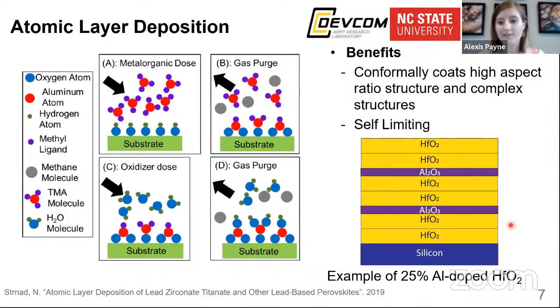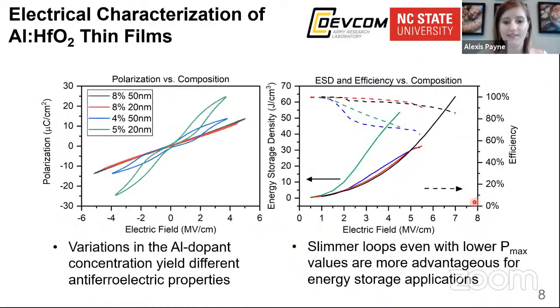In this case, you can see that there are 8 layers, and out of those 8 layers, 2 of them are alumina, making this example film 25% aluminum-doped hafnia. That's a really high doping concentration compared to what we use. We use a doping concentration ranging from 4 to 8%, and our thin films are either 20 or 50 nanometers thick. So to start this work, we first decided to grow our thin films on a planar surface, and we used platinum electrodes. The electrical characterization of the planar films can be seen in this slide.